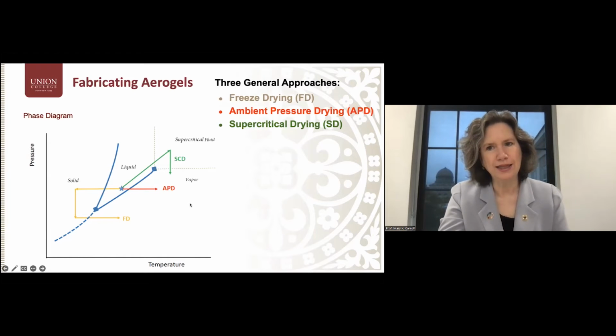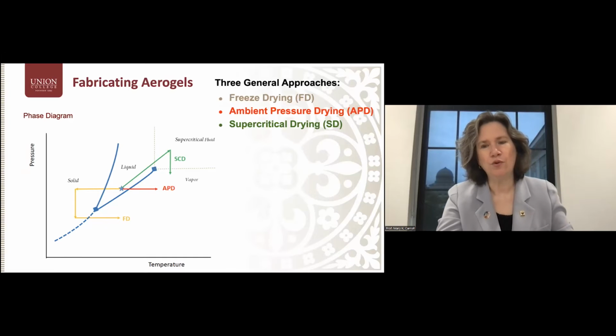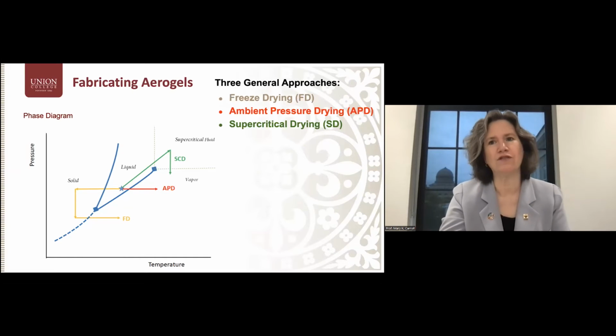So if one wants to make monolithic or single piece large aerogels, the supercritical extraction method or the ambient pressure drying method are generally the ways to go. And for supercritical drying, because of the temperature and pressure conditions, generally what's done is that we start with the wet gel and we exchange the solvent in the wet gel for liquid carbon dioxide, in a pressure vessel. This will generally require multiple solvent exchanges because the solvents in the pores are quite polar and carbon dioxide, of course, is not.